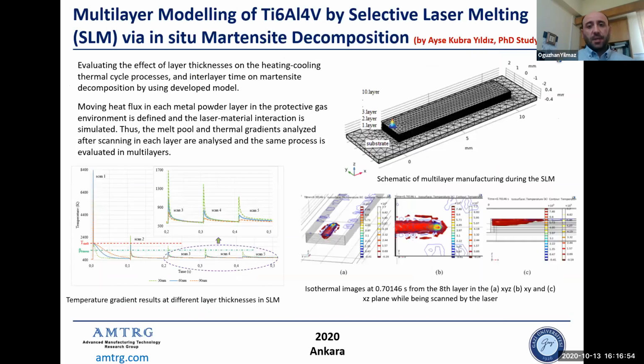Another study, very near to the previous one, is being done by Ayşe Kübra. She's also working on the melt pool, but in this case she's focusing on how we predict the phase transformation during the SLM process. It's based on how much heat we apply to the powder, what the heating and cooling thermal cycles and interlayer time are going to be, and what the martensite decomposition could be.